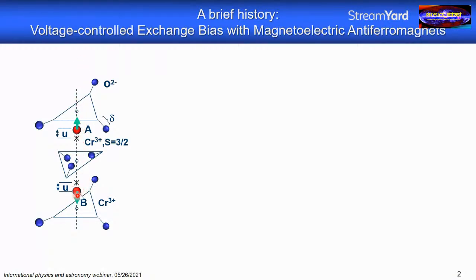Now that chromium 3+ ion sits in an environment of oxygen 2- ions, which has almost octahedral symmetry, but some distortion, as you can see here, indicated by these triangles. This one is a bit bigger than this triangle of oxygen 2- ions. And now we can ask, what happens if I expose this material to an electric field?